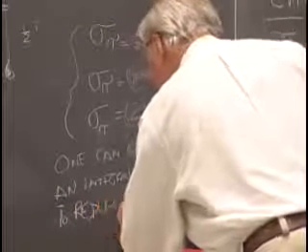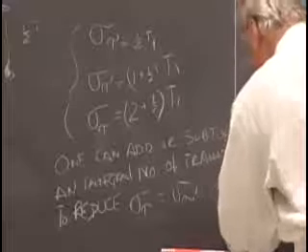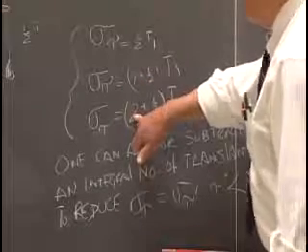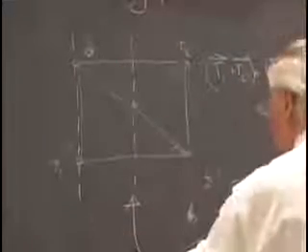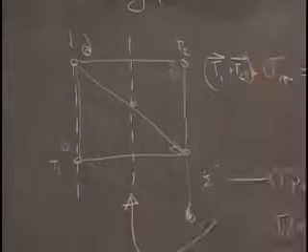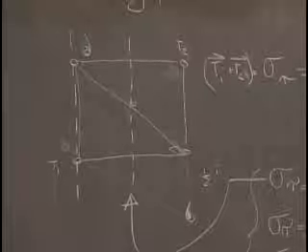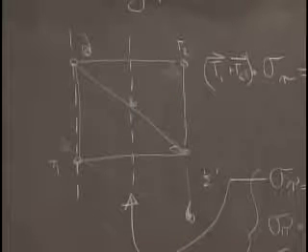And that permits one to reduce any tau to a tau prime, such that tau prime is always less than the translation that's parallel to the tau. In other words, lop off this translation of an entire T1, this translation of the entire T2, and you have identified the basic nature of the glide operation that sits here as something with a translation that's half of T1. The translations that move motifs out of the cell may be related by a glide operation that involves an integral number of T1s plus half a T1, but it doesn't change the basic nature of the simplest glide step that's in there. That's a very obscure explanation of probably something that didn't puzzle you in the first place, but it's worth saying when we make some of these additions.